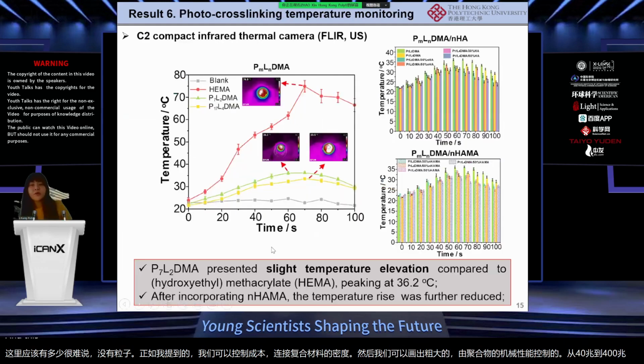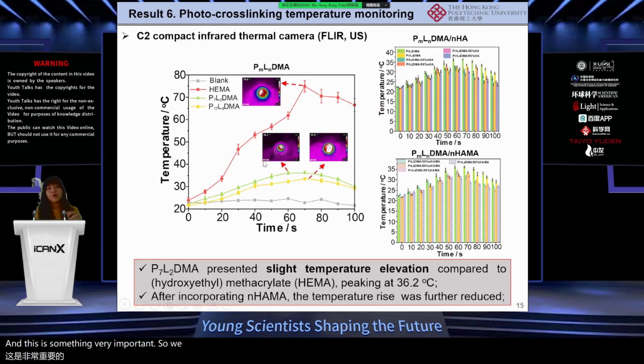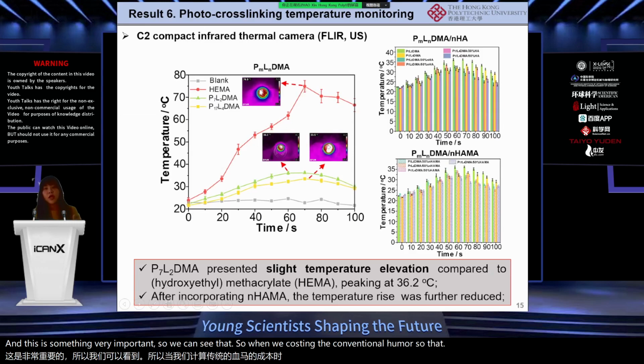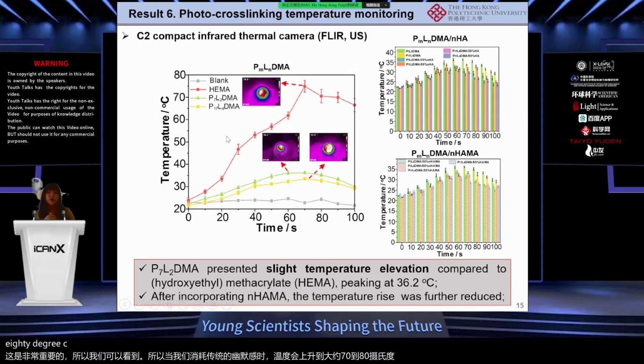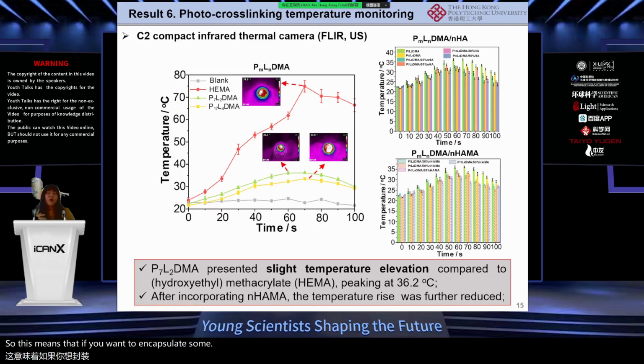And this is something very important. When we cross-link the conventional HEMA, the temperature will increase to about 70 to 80 degrees C. This means that if we want to encapsulate very active bioactive molecules, this will kill these bioactive molecules. But when our polymer cross-links, the temperature will only go up to about 36 degrees. So in this case, our materials can preserve these bioactive molecules.